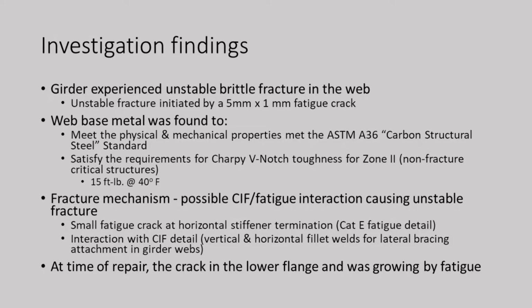We couldn't really tell. And then the last thing is, as we were investigating this out in the field, we were monitoring the growth of that crack in that flange, and it had grown maybe 3/4 or 3/8 of an inch in about a month. So basically fatigue was chewing through it, and they had to promptly repair the girder before that lower flange parted.